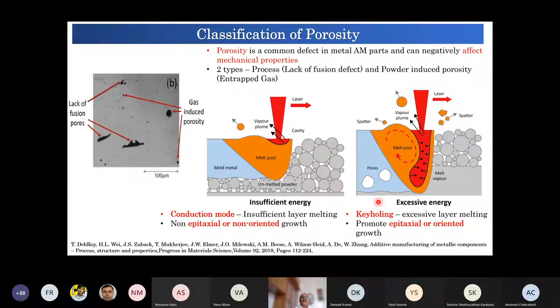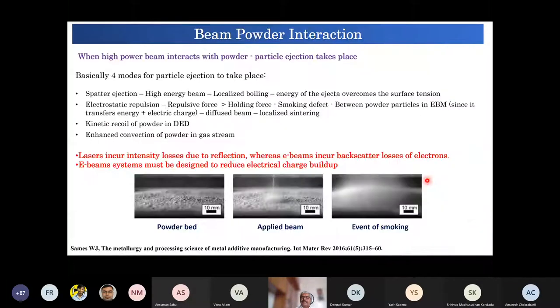Now porosities can be of two types. One is the porosity that comes because of lack of fusion or gas-induced porosity. Here we can see that if there is insufficient energy input, then we get unmelted regions, because the melt pool has this shape generally. This has also been modeled in our group. Here this is the weld metal and this is the melt pool, and slowly as it advances, the weld metal increases, but there is always an unmelted region below this, and this is where lack of fusion porosity comes. Then there is another extreme where there is excessive energy, as I have shown in the previous slide. Then keyhole type defects form. In this condition there is epitaxial or oriented growth, while in this case the growth is non-epitaxial or non-oriented. All these things can lead to defects, which we have to get rid of, right?